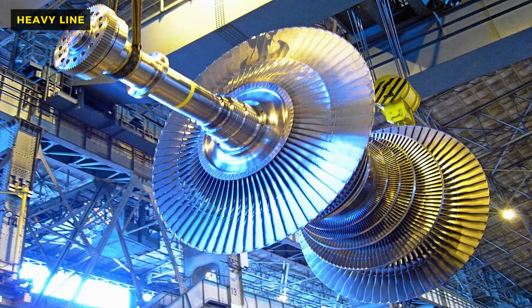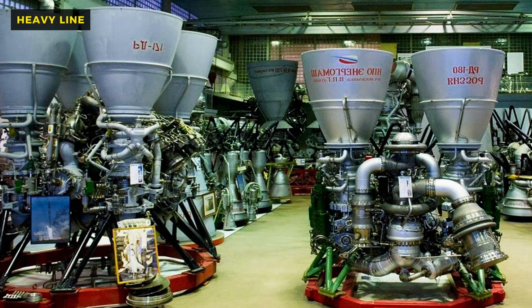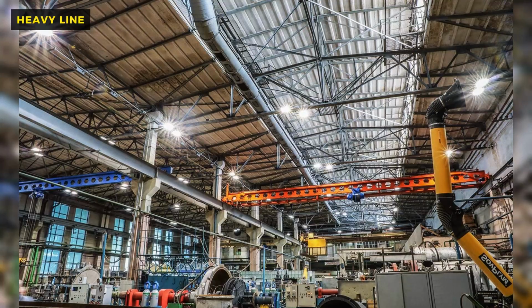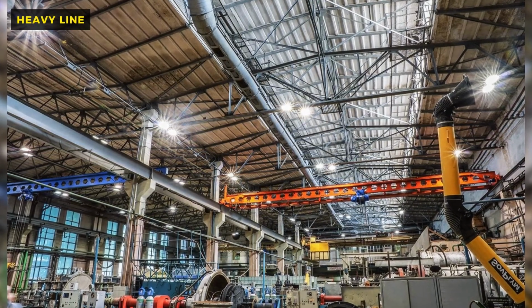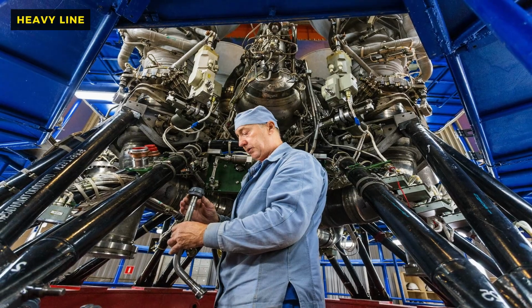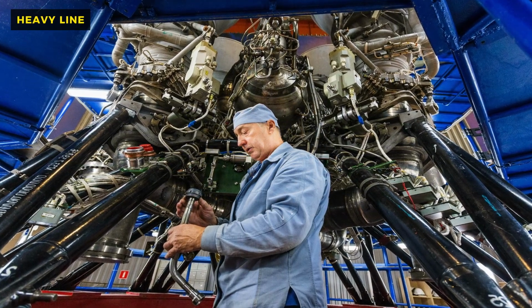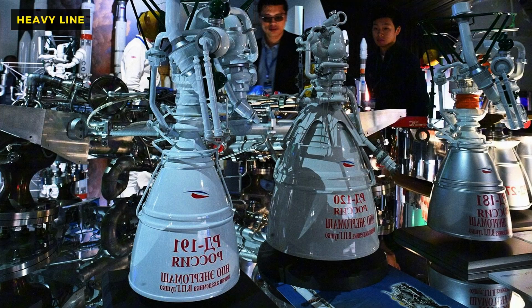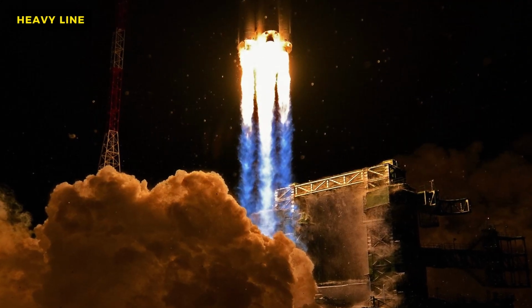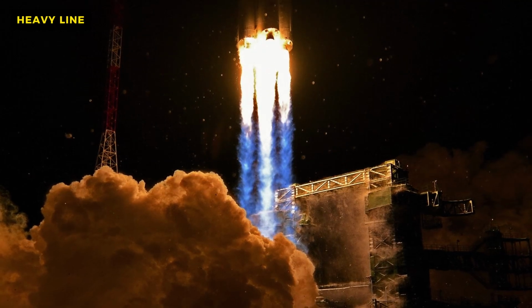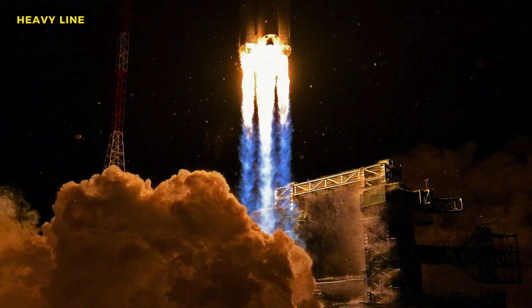The testing phase, known as the green run, is where the rubber meets the road, or rather, where the fire meets the deflector plate. When an RD-180 is strapped to the test stand at Energomash, the preparation takes days. The engine is instrumented with hundreds of sensors, measuring pressures, temperatures, and vibration frequencies. The propellant lines are chilled down, a process that causes the pipes to groan and contract as liquid oxygen at -183 degrees Celsius flows through them. Frost forms inches thick on the outside of the valves, shedding like snow when the system is jolted. The technicians retreat to the blockhouse, a bunker with walls of reinforced concrete several feet thick, and the countdown begins.